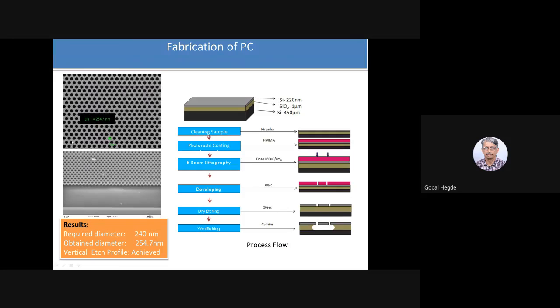The dimensions of this photonic crystal are also given here. You can see the periodic structure of holes and air gaps, the solid structure and the air gap. The hole is the air gap, and this is silicon oxide. The diameter our model showed was 240 nanometer. The diameter we achieved is 254. It's okay, so we are within the range.